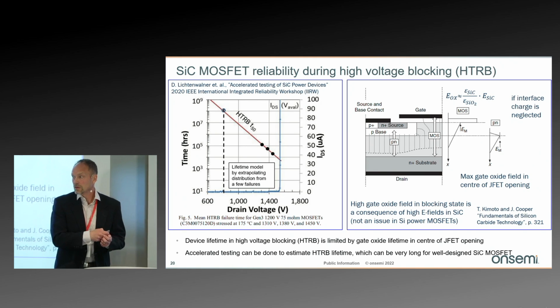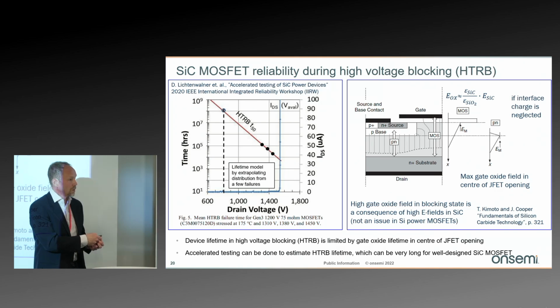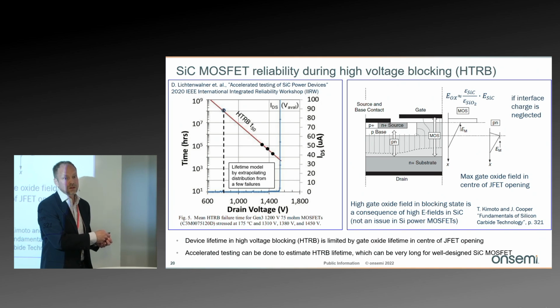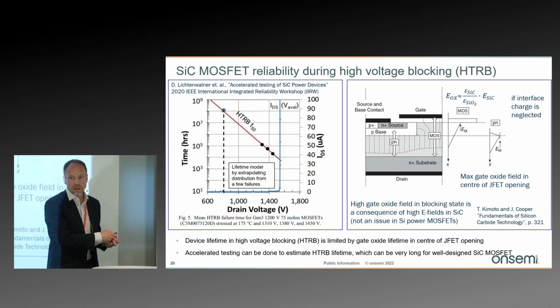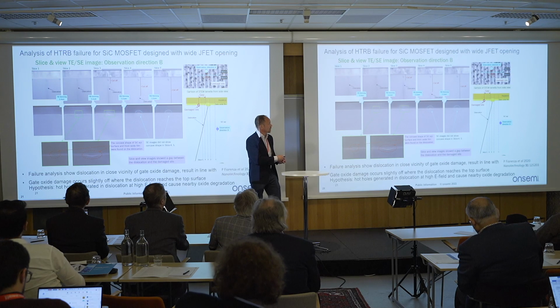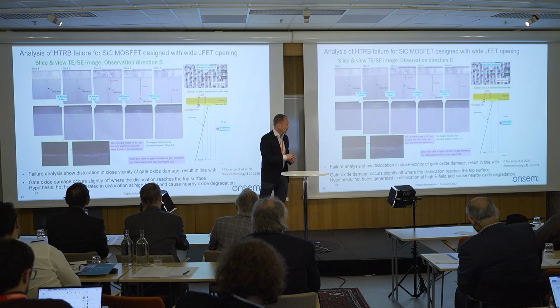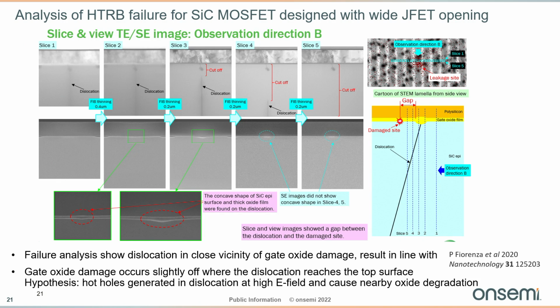It is difficult to do lifetime testing because you have to be really close to breakdown, and if you test into breakdown, then you may start to influence the characteristics. So yes, also very time consuming. One interesting finding I want to share here that I think is not so widespread: in the testing we have limited the current with fuses, so we should not get so much damage, so we can see the failure analysis in detail. And we did cross sections. Here is one that does not intersect with our active cells, so therefore I'm allowed to show it here.